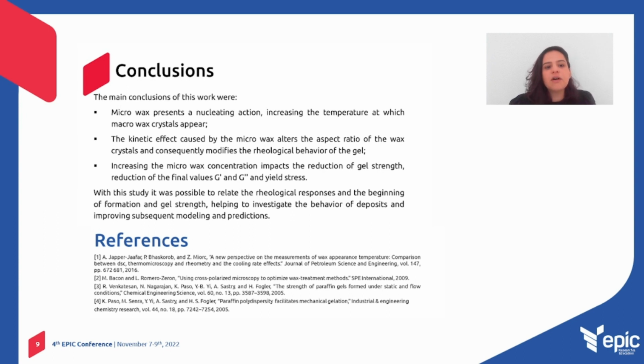And the increase of the micro wax concentration reduces the gel strength, reducing the final values of the loss modulus and the storage modulus, and the yield stress too.